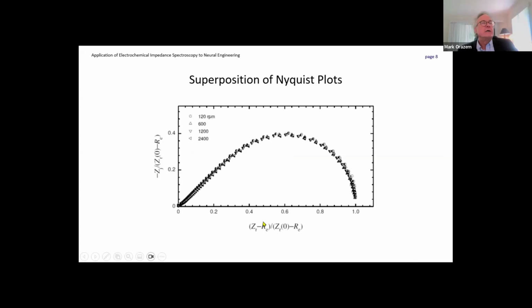If we scale this by the real part at the zero frequency limit minus the ohmic resistance, then for the real axis, we're plotting the real part minus the ohmic resistance. On the imaginary axis, we're plotting the imaginary part divided by the same thing we're using to divide the real part by. And what we see is that all those data that we were showing you on the previous slide superpose very nicely. It's a way of showing you that the chemistry and physics has not changed, just the rotation speed.